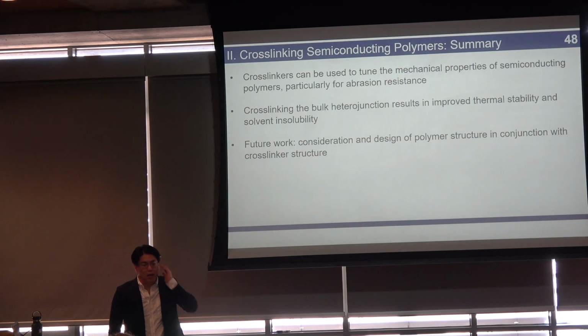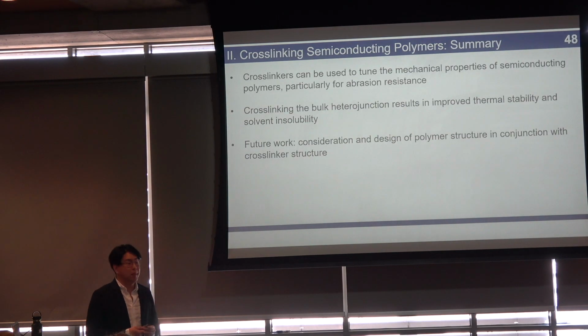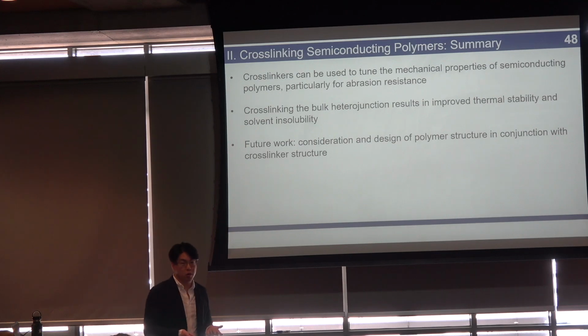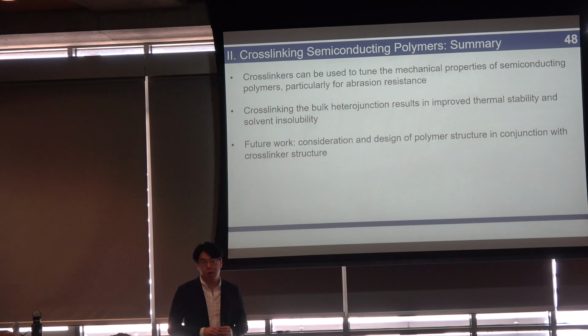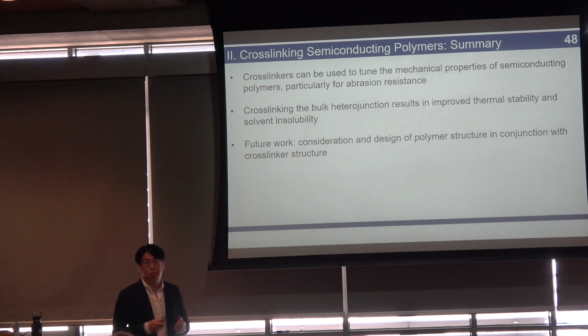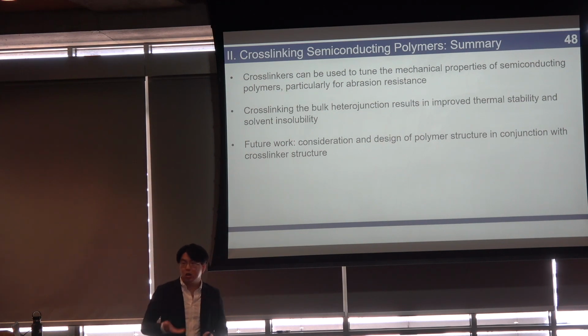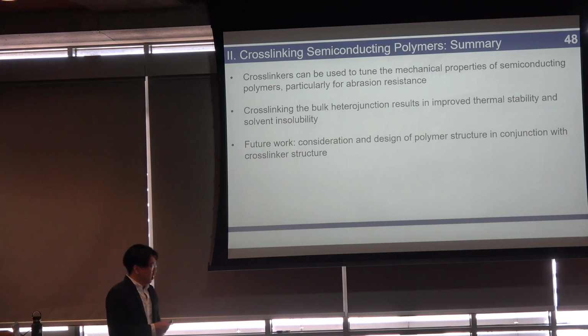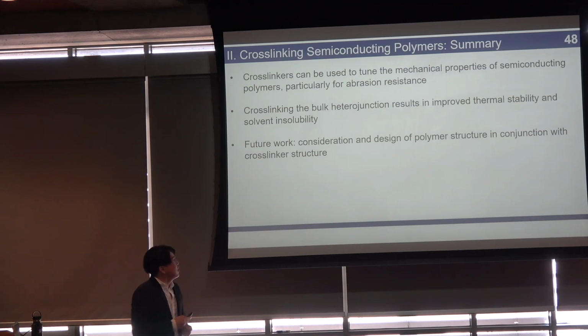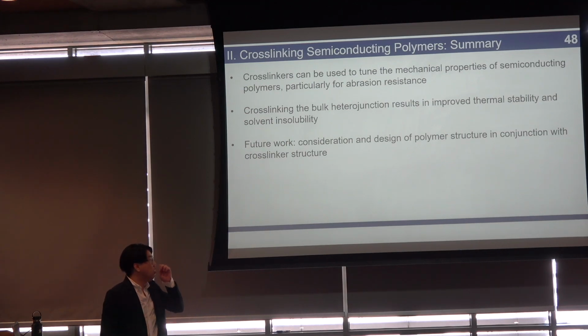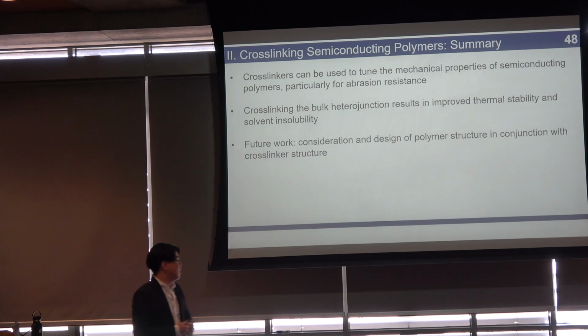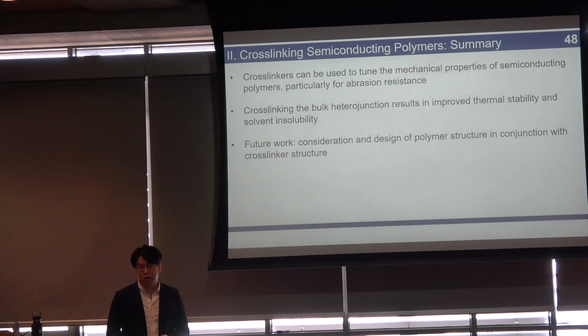So just to quickly summarize, we see that cross-linking is a method that's very common to conventional polymers, but we can actually use this to tune and optimize the mechanical properties that we care about, in particular, abrasion resistance. An additional benefit is the thermal aging and the insolubility of your film, but that's already been explored. So if I was to redo this project, or work on this in the future, I would recommend some stronger considerations about the structure of your polymer and your cross-linker.